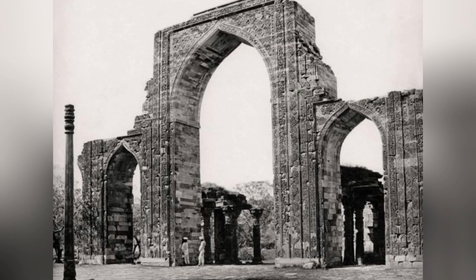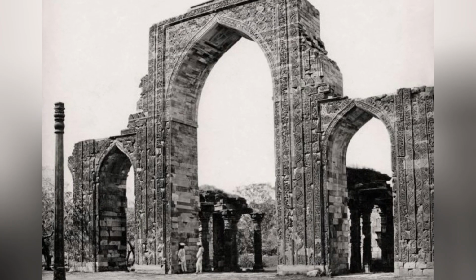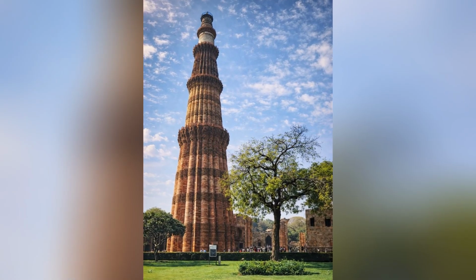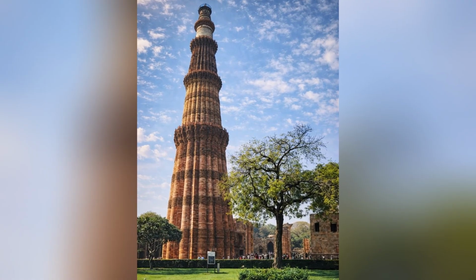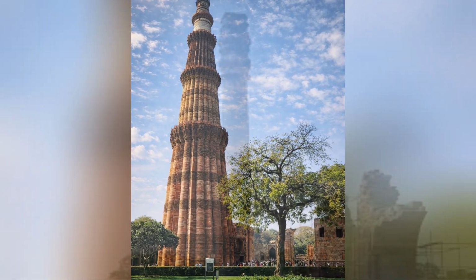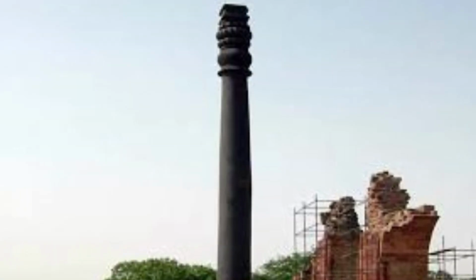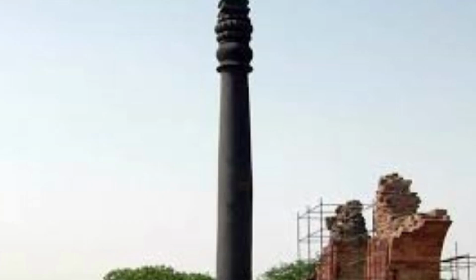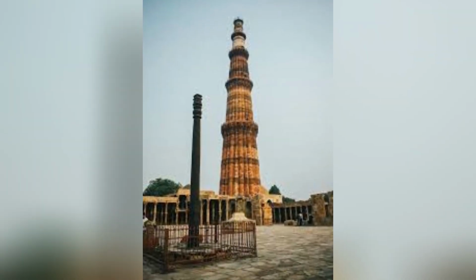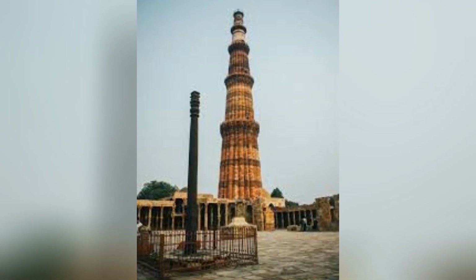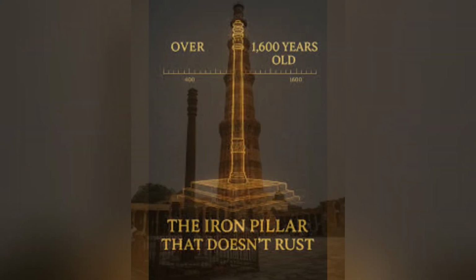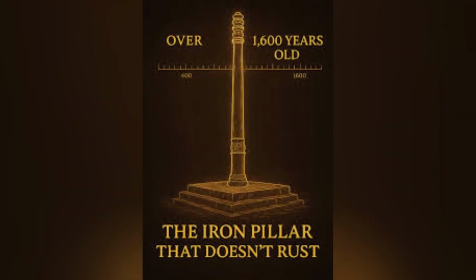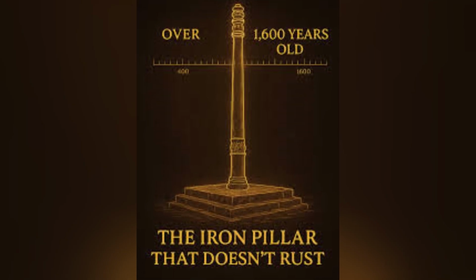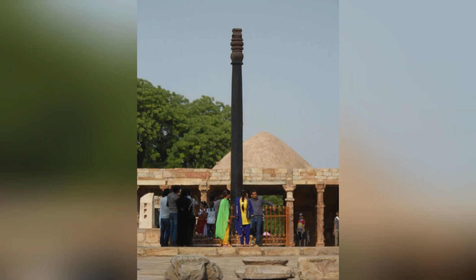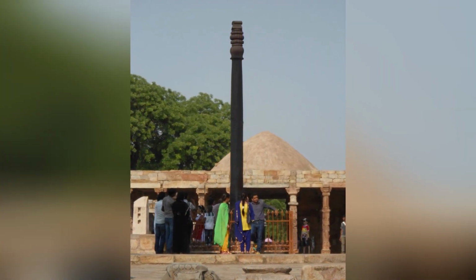The investigation of the iron clamps that were used to hold together the stone blocks of ancient Indian temples has provided additional comparative evidence. These iron clamps, which are found at temple sites across India, are made of bloomery iron that is often similar in composition to the Delhi pillar's iron, and many of them exhibit corrosion resistance that is consistent with the phosphorus-mediated protection mechanism that has been identified in the Delhi pillar. The iron clamps provide evidence that the corrosion-resistant properties of Indian bloomery iron were exploited, whether intentionally or accidentally, in a wide range of structural applications, not only in the production of monumental pillars, but also in the everyday construction practices of the ancient Indian builders.